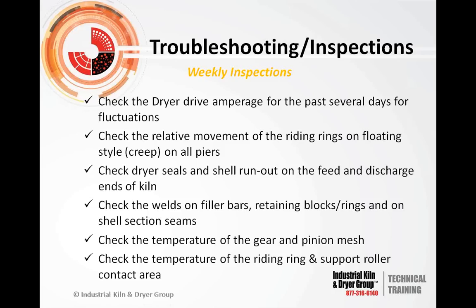You can also use an infrared gun to check the tire and riding ring and support roller trunnion contact area. This is a good indication of whether you've got a roller skewed excessively. If it's really skewed in hard, you may see a high temperature on one side of the roller versus the other side. So these are things you would like to check on a weekly basis. Here again, this is more for recording purposes, so that down the road, you have a trend of how your units are operating over an extended period of time.